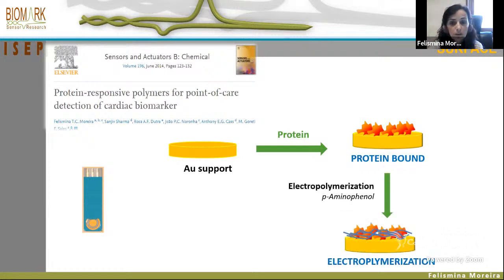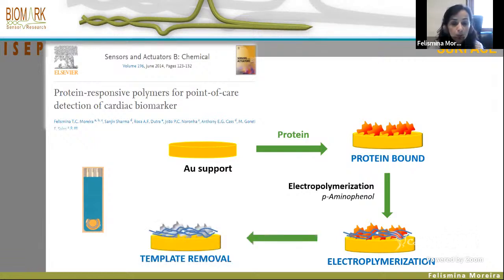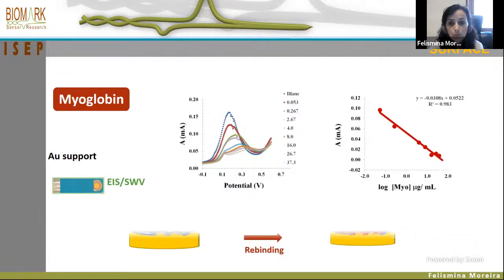In this case, the polymerization was performed by one electrical stimulus, potential, and we used aminophenol as a monomer, and the template removal was performed by using proteinase K, an enzyme, which was a more friendly and soft procedure. The analytical performance of the biosensor was evaluated by square wave voltammetry, one electrochemical technique.